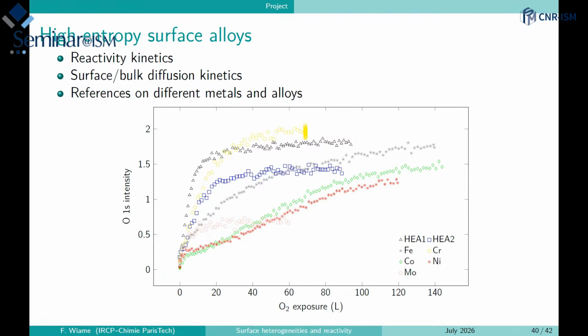And you can see that we have studied 2 specific high entropy alloys with slightly different composition. You can see, for example, that with this one, we have a reactivity which is much higher. So the idea is that we have some synergetic effect that makes the reactivity of the high entropy alloy larger than the reactivity of all of the others, which obviously would be interesting for catalysts, for example. This is also called the cocktail effect, that the cocktail is better than every component.